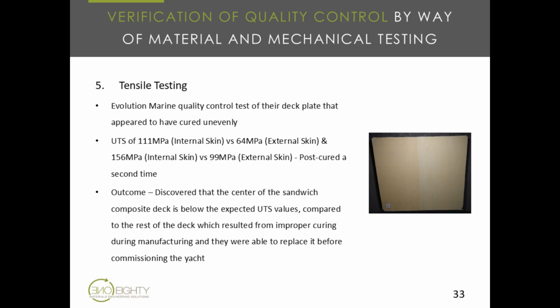So through our testing, we found that the ultimate tensile strength of the internal skin was 111 megapascals, while the external skin was 64 megapascals. So there's a complete and significant difference in tensile strength of the two materials that are supposed to be exactly the same. They thought perhaps it might not have cured properly, so they tried a second cure. And after that, there was still a difference between the two. As you can see, it was 156 megapascals for the internal skin and 99 megapascals for the external skin.